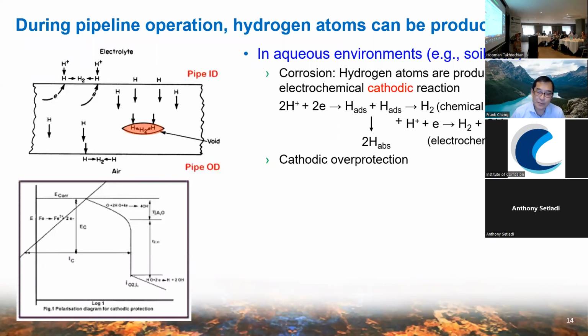You can see from these slides, hydrogen atom can be produced by the hydrogen evolution reaction. It's an electrochemical reduction of hydrogen ions. And then the hydrogen atoms, H ADS, can combine into hydrogen molecule H2. If the H2 is produced by either chemical recombination or electrochemical recombination, then we don't worry about hydrogen embrittlement because the hydrogen molecule cannot go into the steel. However, a certain percentage of the H ADS can go into the pipeline steel and become H ABS. So this is the main mechanism, hydrogen generation and hydrogen permeation from the corrosion reaction.